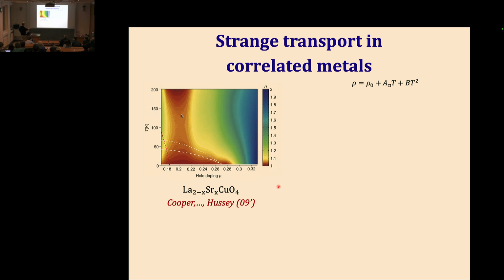But interestingly, you see that this fan is actually not confined to a point. This lower dashed line is Tc. You can suppress superconductivity by applying a very high magnetic field. You need an extremely high magnetic field, tens of Tesla, because Tc is so high. But if you do that, you reveal a normal state at very low temperature, where the resistivity actually continues to be linear down to the lowest accessible temperatures over an entire range of parameters, not just at the point.